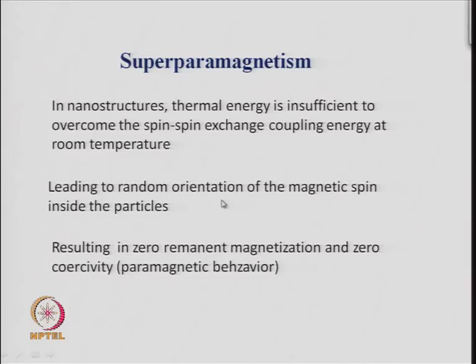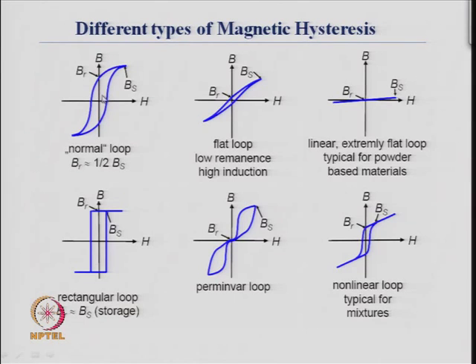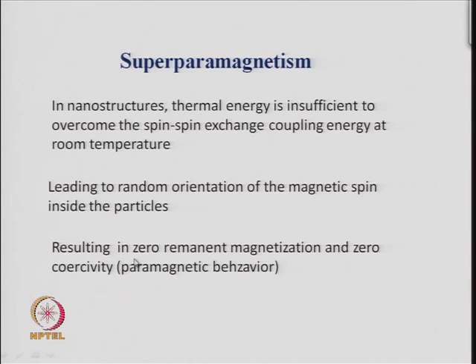And this kind of random spin leads to zero remanent magnetization and zero coercivity, which is like a paramagnetic behavior. So, not like a ferromagnetic behavior. In a ferromagnetic behavior, you will have a remanence, and you will also have a coercive field. That means the plot will not go through zero. Whereas, whenever you have zero remanence and zero coercive field, the line will go through the origin. That means you need no energy to bring back the sample from its magnetized form to the zero form, where there is no magnetization. So, that kind of result, where the net remanent magnetization is zero and there is zero coercive field, is a kind of paramagnetic